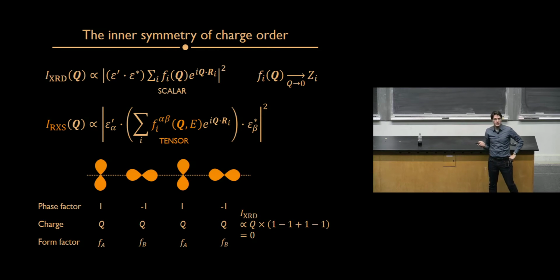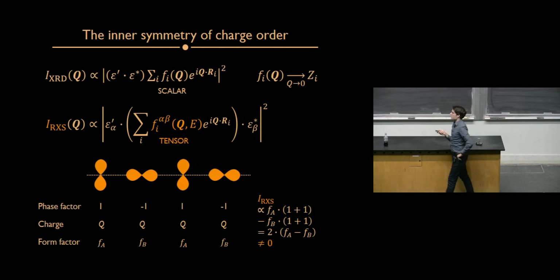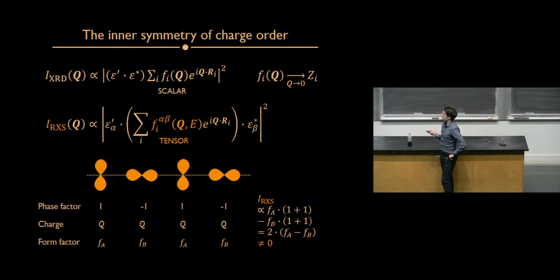This gives me 0, so I cannot see this with diffraction, even though it's an ordered arrangement of orbitals. If I do this with scattering instead, well, these two lattice sites have a phase factor of 1, and they have the same form factor, Fa. These two sites here have a phase factor of -1, and they have a different form factor, Fb. So in the end, if you take this summation, you get 2 times (Fa minus Fb), which is different from 0 because these two tensors are different. So with resonant X-ray scattering, you can measure orbital patterns like this.